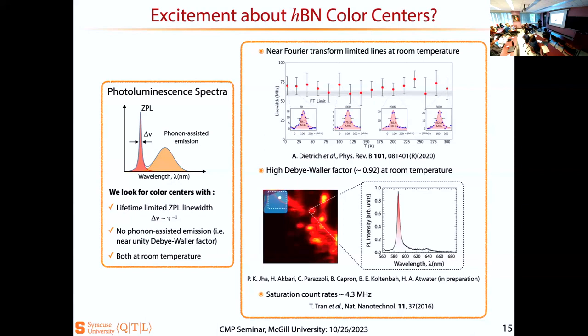So one paper which came in 2020, in which the same group which showed the presence of the color center, they also reported a paper in which they said, at room temperature, they were able to observe transform limited or lifetime limited absorption lines. So that was, like I said, a huge game changer. But since then, we haven't seen any other paper reported out. So what was so special about that crystal or that molecule that they were able to observe? And I haven't seen any other paper yet, so I don't know whether it has been reproduced or not. Recently, in the last paper which I worked on, we were able to get near transform limited, but at cryogenic 6.5 Kelvin. We were able to reproduce this, but at cryogenic, not at room temperature. Okay. So this is one really good motivation.